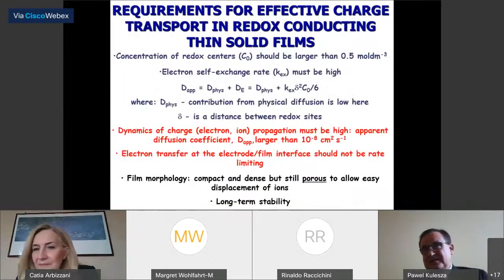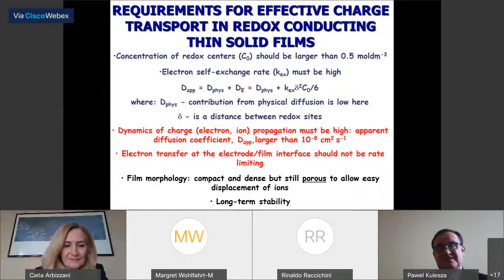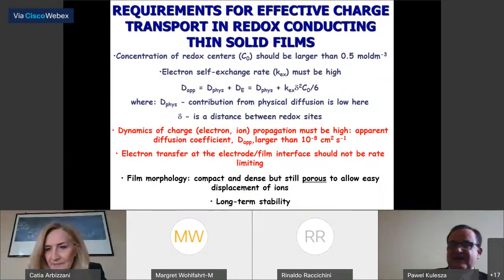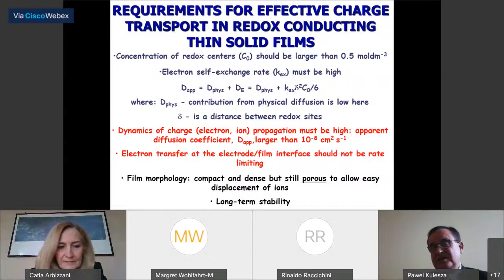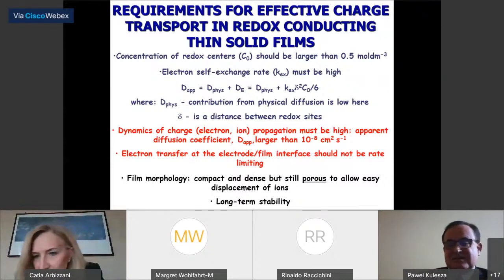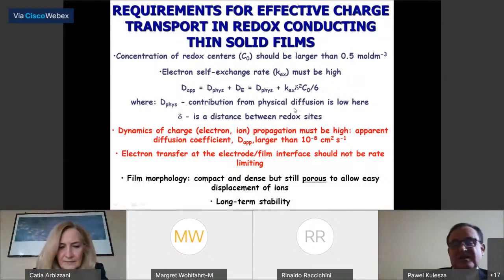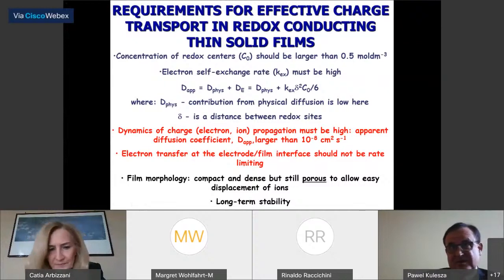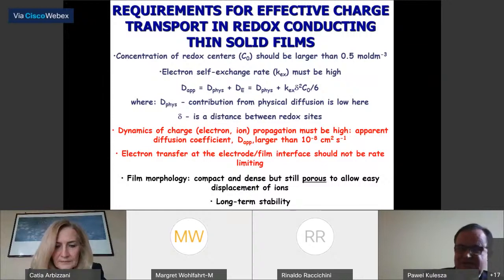So if we go to the solid state materials, Prussian blue type systems, to make them effective in charge propagation, I would like to say that we need to meet certain requirements which are summarized by the Dahms-Ruff equation. It means we need to have a high concentration of redox sites, short distance, and high self-exchange rate. And of course, the counter-ion motion is very important. And most of Prussian blue analogs with potassium meet this requirement.